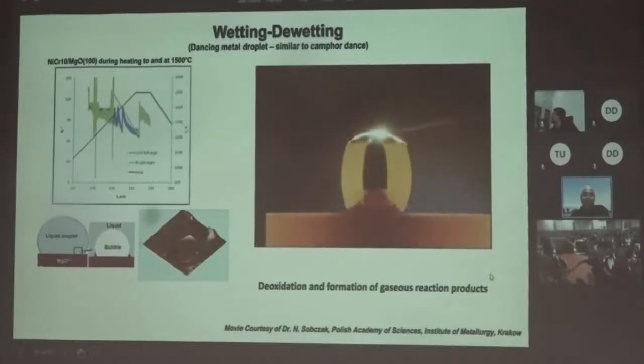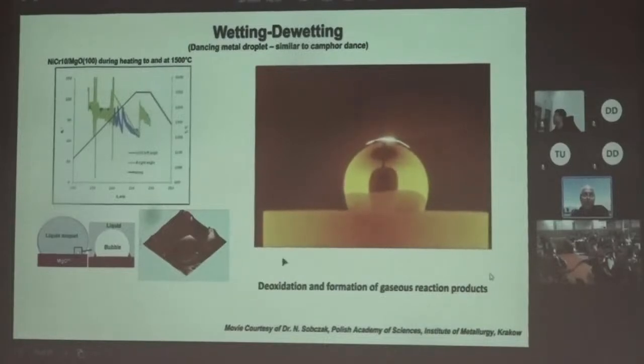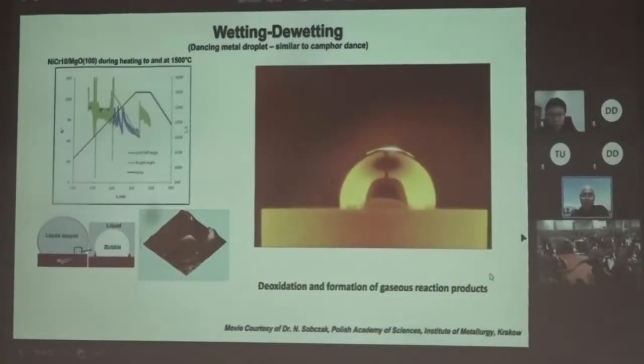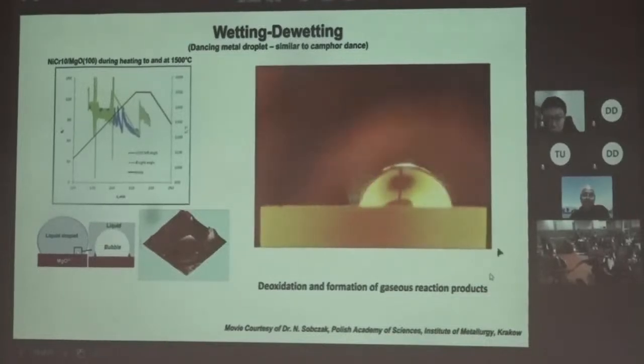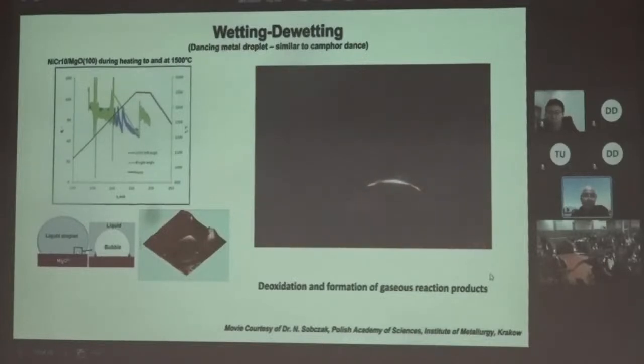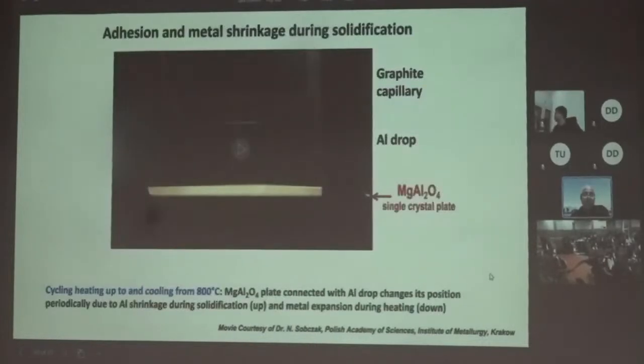Another example is wetting and de-wetting. Under high vacuum, when this little droplet melts, there is some reaction taking place and teeny bubbles can form underneath. You will see the droplet jump up and down because of the bubbles escaping. You will see that in a few seconds. This is what is happening now. The time is actually almost 30 minutes, but we have high-speed videos here. So there are a lot of effects taking place.